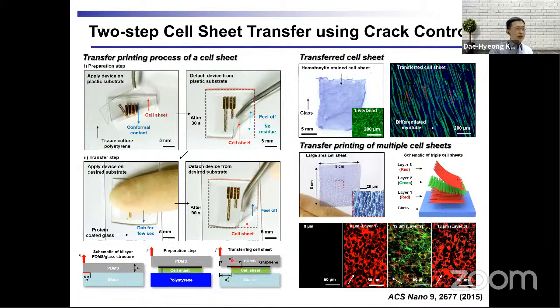After generating the crack, if we make a contact of the cell sheet to a target substrate such as protein-coated glass or the target region of the heart, the cell sheet will make a good contact to the target substrate. And if we gently remove the PDMS stamp, then the cell sheet can be simply transfer printed, as shown in this image and this large-area cell sheet transfer printing image.